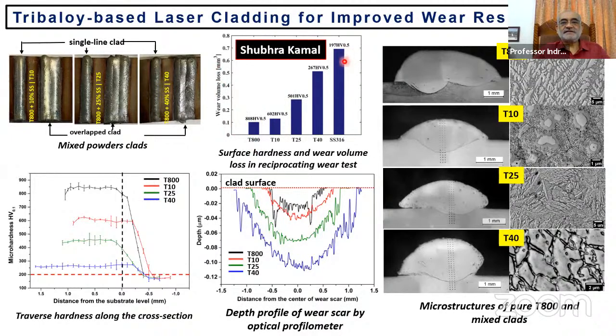You can easily see that as we take stainless steel and compare with various forms of Tribaloy's, with Tribaloy 800, the wear volume is the least. So obviously this is the most wear resistant material possible. So these are the varieties that we are seeing. And here is an interdiffusion zone, but this is the clad layer. And this is the top microstructure.